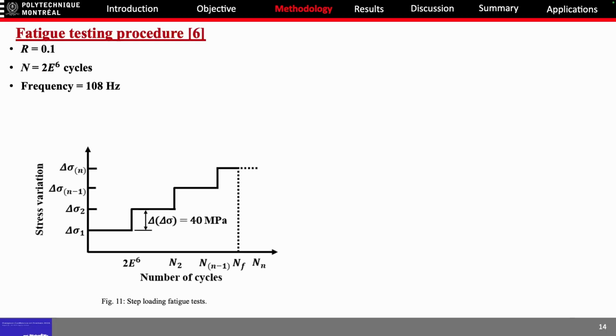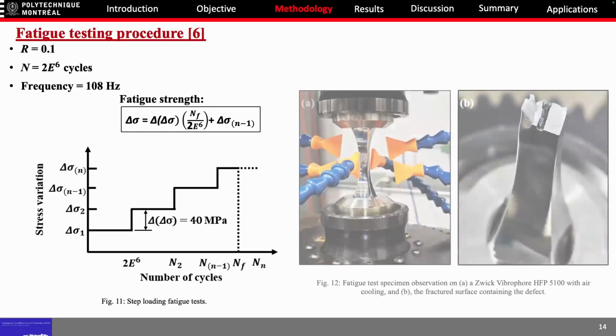So for the fatigue testing procedure, a load ratio of 0.1 was applied with a targeted number of 2 million cycles. A frequency of 108 Hz was used because we used a Vibrophore. To calculate the fatigue strength, a step loading method was used. Basically, the last two steps of this method are used in this equation.